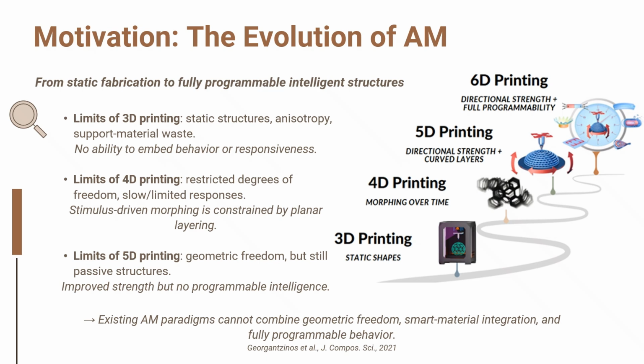To understand why 6D printing is needed, we have to look at the evolution and the limitations of the technologies we already know. 3D printing gave us geometric freedom, but the structures are static, anisotropic, and often wasteful because of support materials. Most importantly, there is no way to embed behavior or responsiveness into a 3D printed object. 4D printing attempted to change that. By using smart materials, structures can morph over time in response to heat, moisture, light, or other stimuli. But the problem remains. The response is constrained by planar layer deposition. The morphing is slow, limited, and fundamentally restricted by the 3-axis printing process.